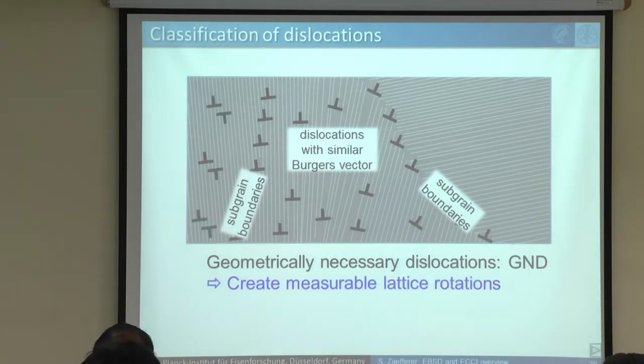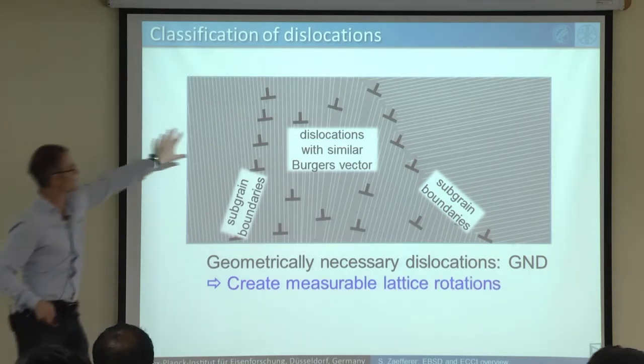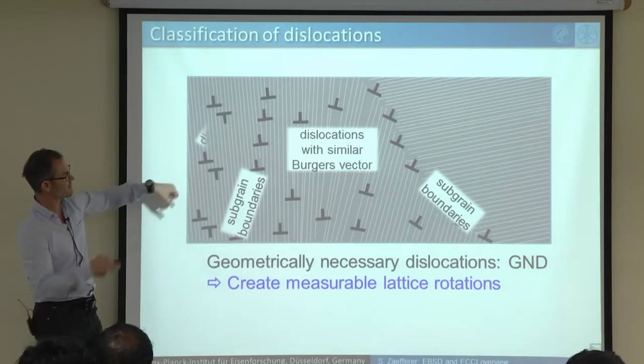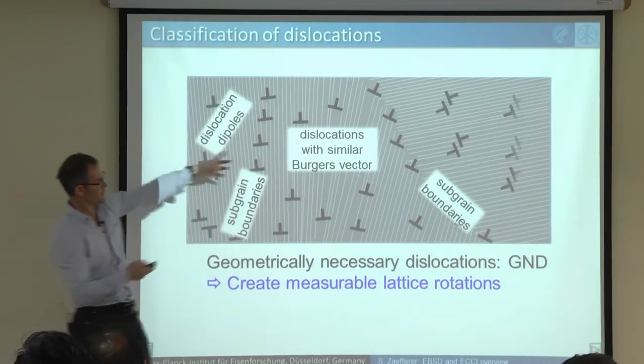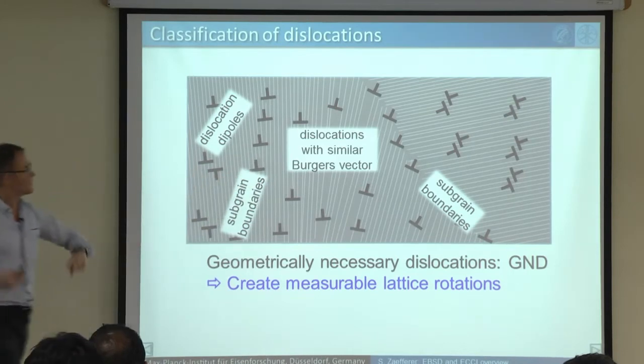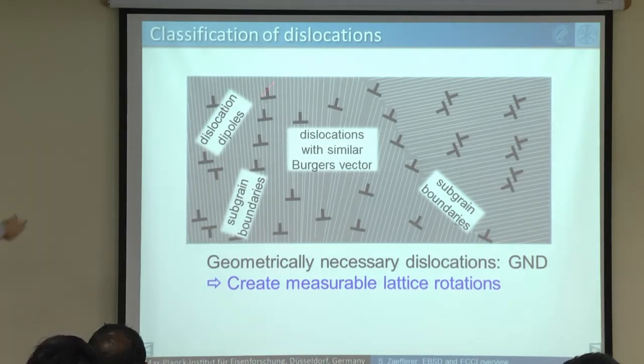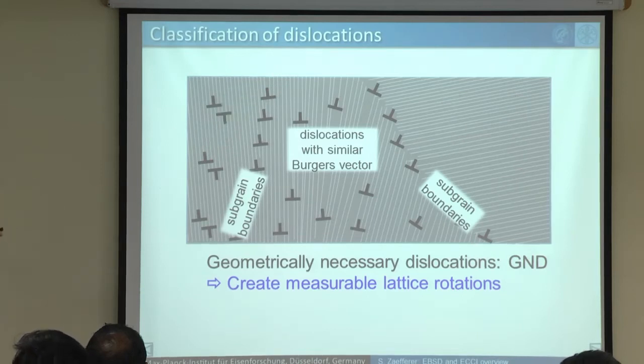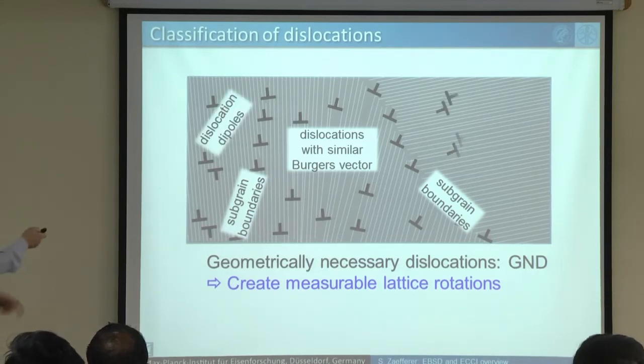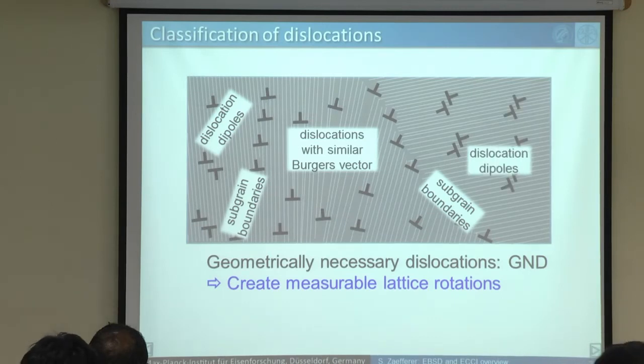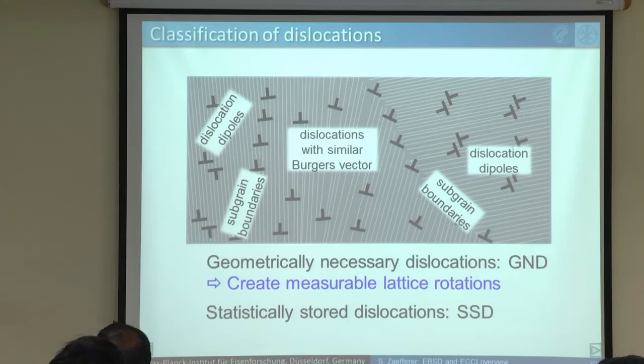They create measurable lattice rotations. Now you may, however, in this lattice here have dipoles of dislocations, and you may have the same thing here, dipoles. You have a plus and a minus dislocation, together no rotation. Although there may be many of these dipoles, a very large amount of stored dislocations, you will not see them with EBSD, at least not by a misorientation. So as a result, these dislocation dipoles cannot be seen, and we call them statistically stored dislocations.